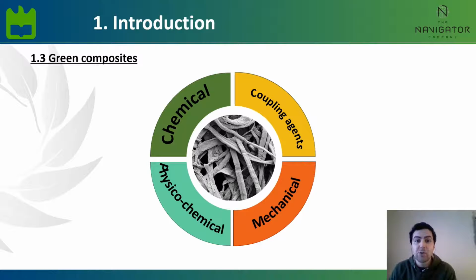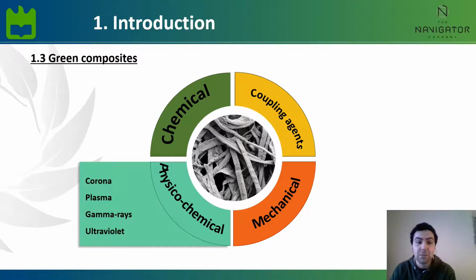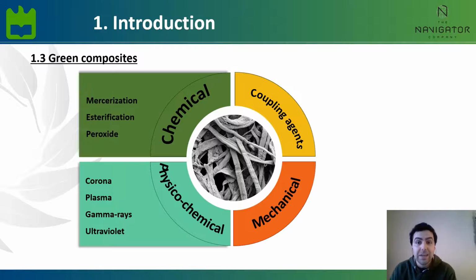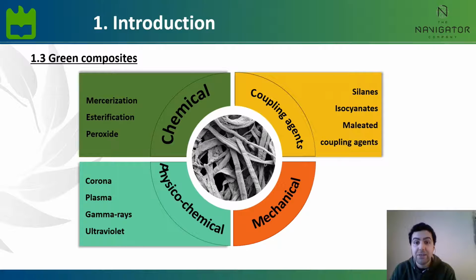Along the years, several strategies have been tested with the aim to overcome some of these challenges. These strategies range from physical-chemical treatments such as corona, plasma, or gamma rays, to chemical treatments such as mercerization or surface modifications like esterification, whose aim is to decrease the hydrophilicity of the fibers through the incorporation of more hydrophobic groups. Then we also have the use of external additives, such as silanes or isocyanates, and the efficiency of compatibilization depends on the ability of these molecules to link both the matrix and the fibers through covalent bonds.